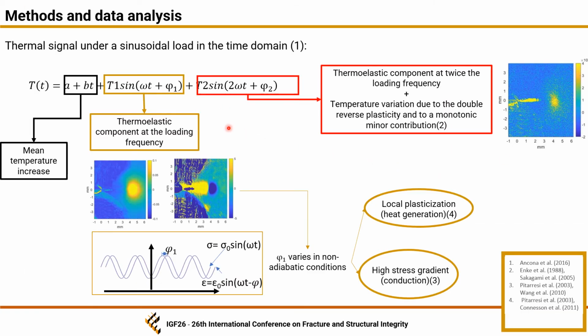In this slide, we can see the temperature variation that can be obtained by using a signal reconstruction algorithm based on the least square method to extract the thermoelastic signal from temperature. We can see in this slide also the other quantities that can be used to study, from the point of view of a reversible process, the phenomena associated with fatigue crack. But in this case we will focus on this term and this term that is related to the thermoelastic temperature variation.